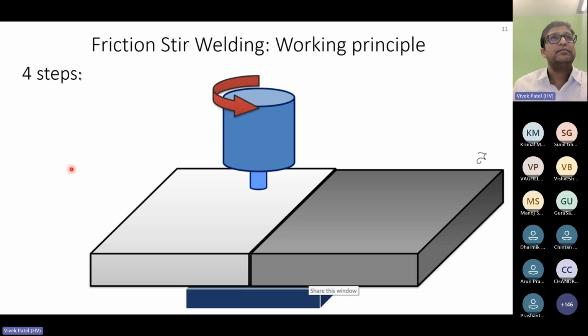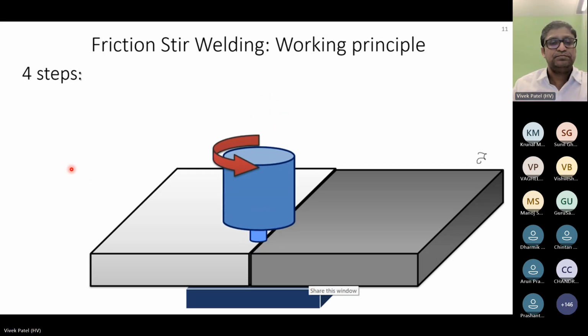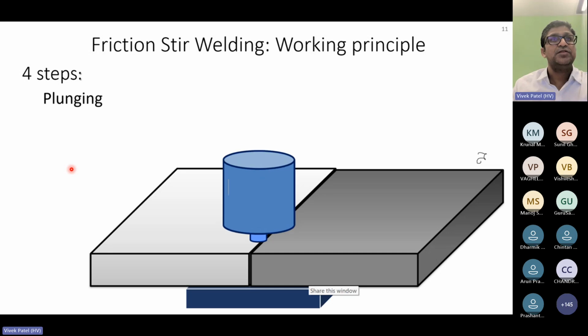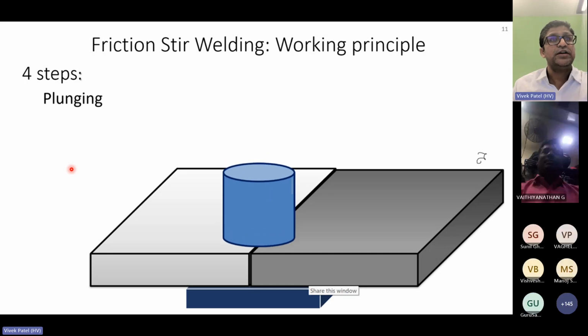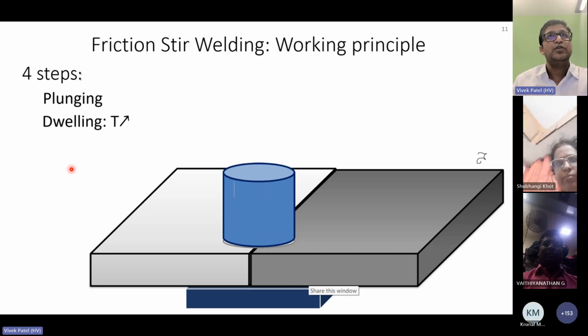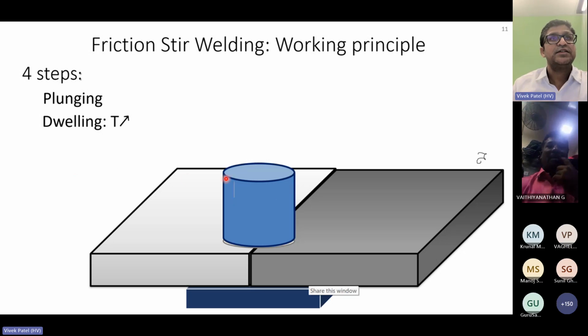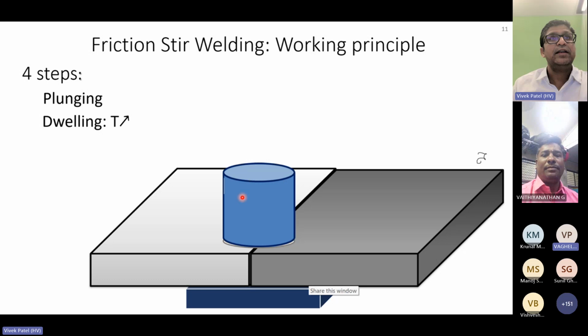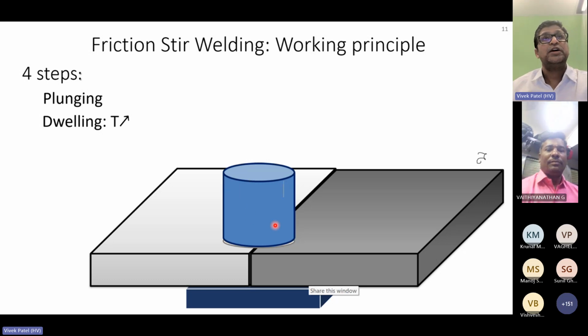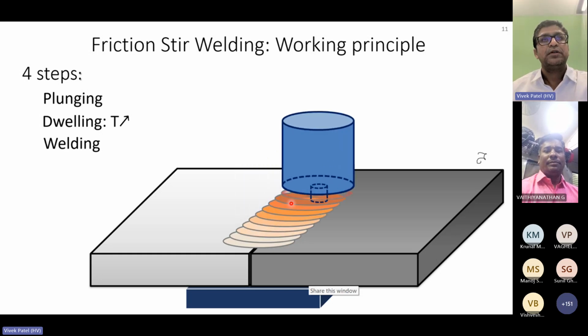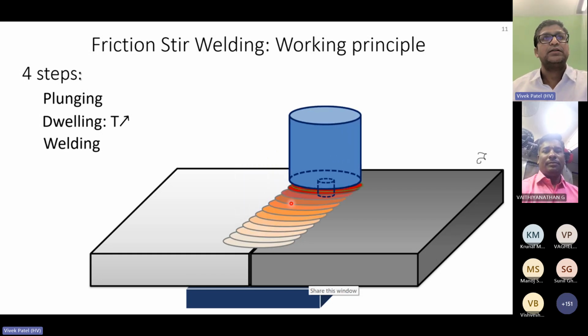So the first step is plunging. The tool makes contact with the workpiece and you wait a certain time. That's called dwelling. And the dwelling time basically depends on what temperature you want to weld at. So once the temperature is reached, then you will start moving this tool in the welding direction. So the second step is welding. So the tool is moved along the welding path.